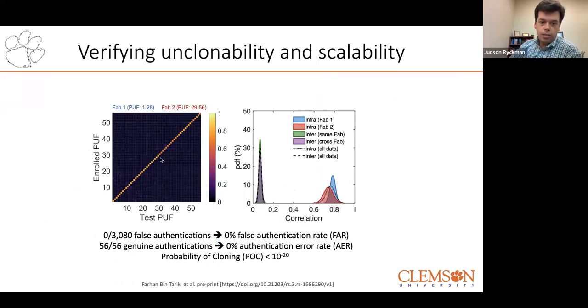So if we analyze the results of all 56 devices, we see nice correlation with themselves, meaning we have genuine authentication with a 0% error rate. And we also had a 0 false authentication. So no two devices accidentally had the same signature.